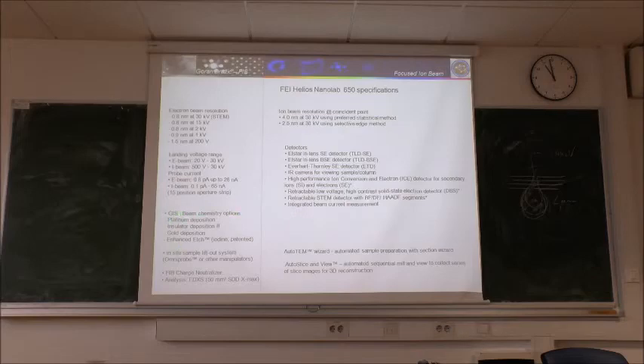We have 4 different gas injection systems. We can deposit platinum, an insulator which is based on silica, silicon oxide, gold, and we also have enhanced etching using iodine, so that we can improve etching by a factor of 10 or 20, just due to the chemical reaction of the surface atoms with iodine. Of course, we have in situ sample lift out, charge neutralizer, and the resolution for the ion beam is around 4, depends on how we measure, 2.5 nanometers. Compared to the electron beam that is much worse, but still you can get nice images at magnification of up to 20,000, 50,000.